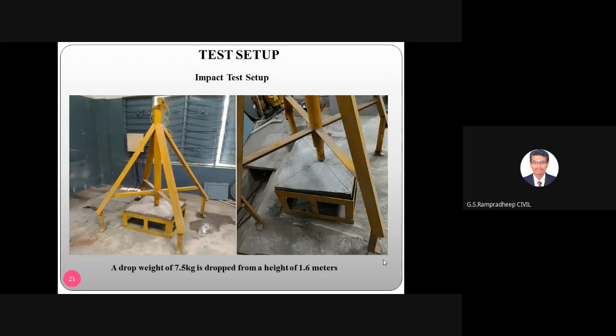Here you can see the impact test setup. This is the impact testing machine we have fabricated in our lab, the yellow color and the base, that base element, the structural supporting element you are seeing, that we have fabricated. This is a drop test where the standard hammer weight is 7.5 kg, and we are dropping it from 1.6 meters. And we have given the provision for the drop.